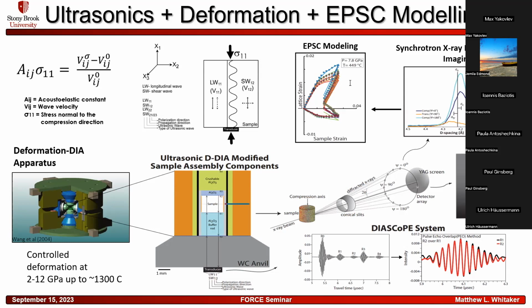And you can see in the top right diagram there that as you move around the circle of detectors, there is a marked difference in the position of the d-spacing of the peak. And that's exactly what we want to measure. That's that ellipticity that starts to form that we talked about earlier.